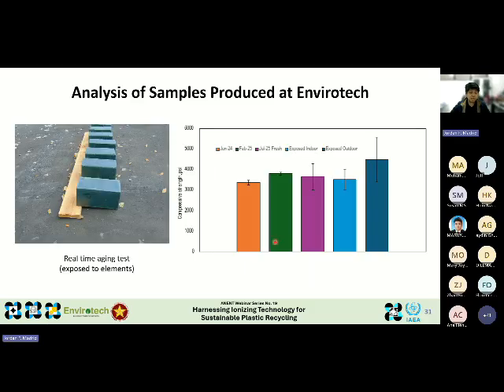The results are plotted here for everyone's appreciation. The compressive strength test results remained very consistent across different testing periods, showing that the performance of the blends is reproducible over time and over different feedstock used. If you look at the results of the 5-month aging test, the last two bars where we had samples exposed indoor and outdoor, we observed that their compressive strength did not change significantly compared to the values obtained from the earlier runs.